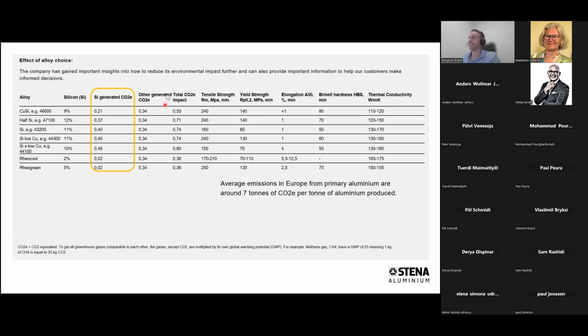And then we have the other generated, and here we have not looked into detail. Of course, there will be some differences here with the other generated CO2 as well between the different alloying groups, but we believe that it should be minor differences between the alloying groups. And then you have the total as well, then the total CO2 impact of the different alloying groups, and the total is of course then the other plus the silicon generated emissions. And then if you look at the Rheo alloys, as I mentioned, they are very low in silicon content, meaning that you have to add, of course, very little silicon. So it's very close to zero, meaning that they have the lowest total emissions.